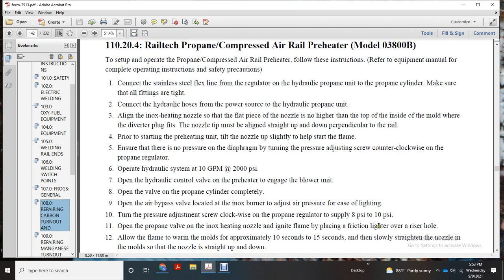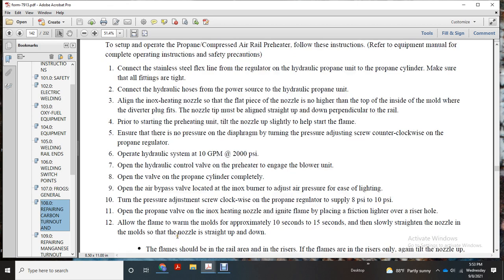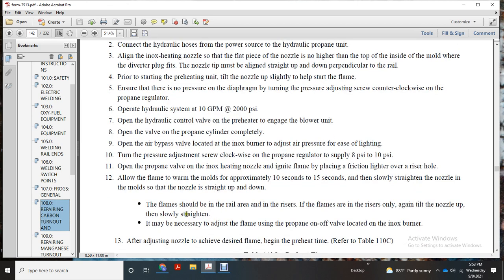Ignite the flame by placing a friction lighter over the riser. Hold the flame to warm the mold for approximately 10 to 15 seconds. Then slightly straighten the nozzle in the mold so that the nozzle is straight up and down. The flame should be in the rail area and the riser, not the riser only. Again, tilt the nozzle up and then slowly straighten it as necessary to adjust the flame. Use the propane on and off valve located on the inox burner. After adjusting the nozzle, achieve the desired flame.